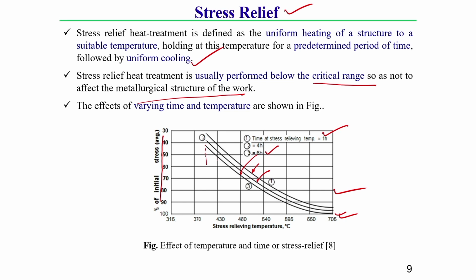So, for a particular temperature, let us consider 430 degree centigrade. If your holding time, here, you can say initial temperature relief, that means removal of residual stress. For 430 degree centigrade, if we hold for 6 hours, then you can see around 55% stress relief is done. Stress relief is done means 55% residual stress is removed.